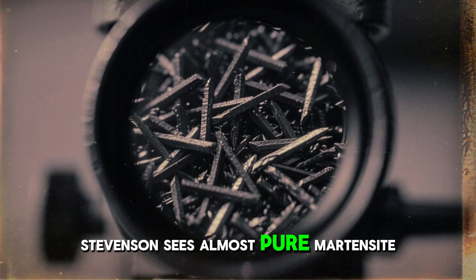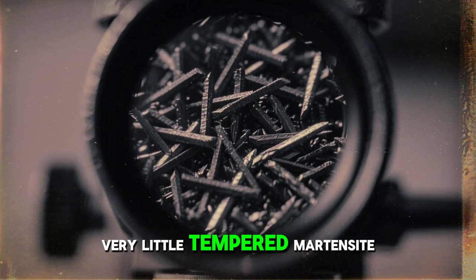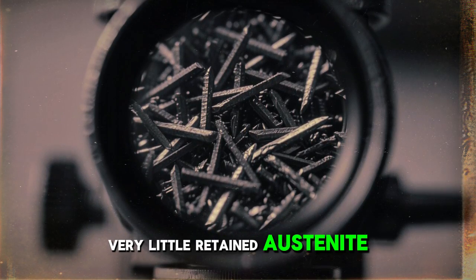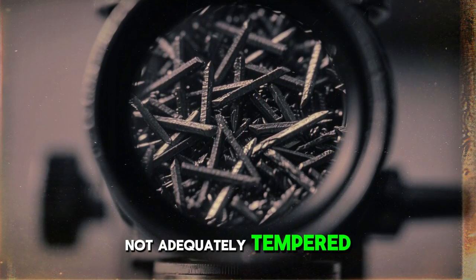Stevenson sees almost pure martensite in the case. Very little tempered martensite, very little retained austenite. The steel was hardened but not adequately tempered afterward.